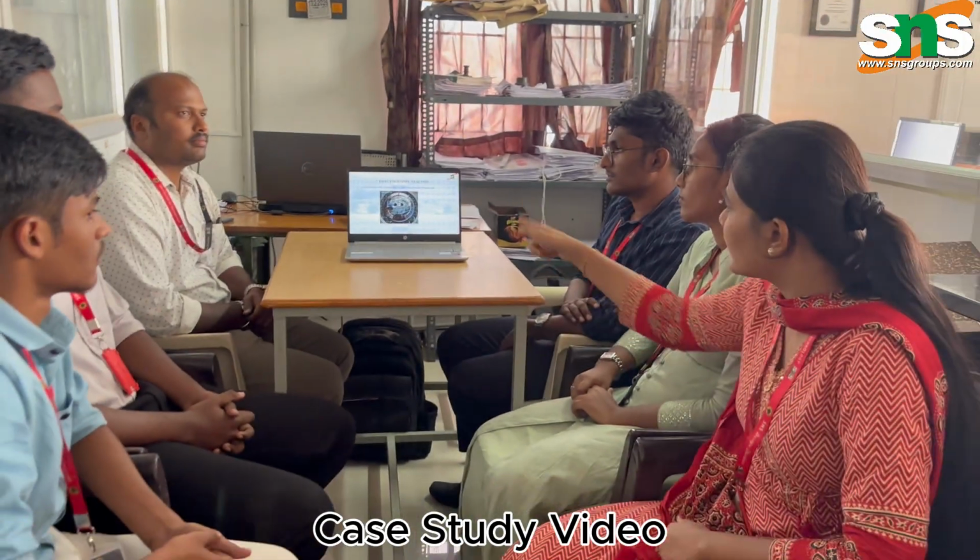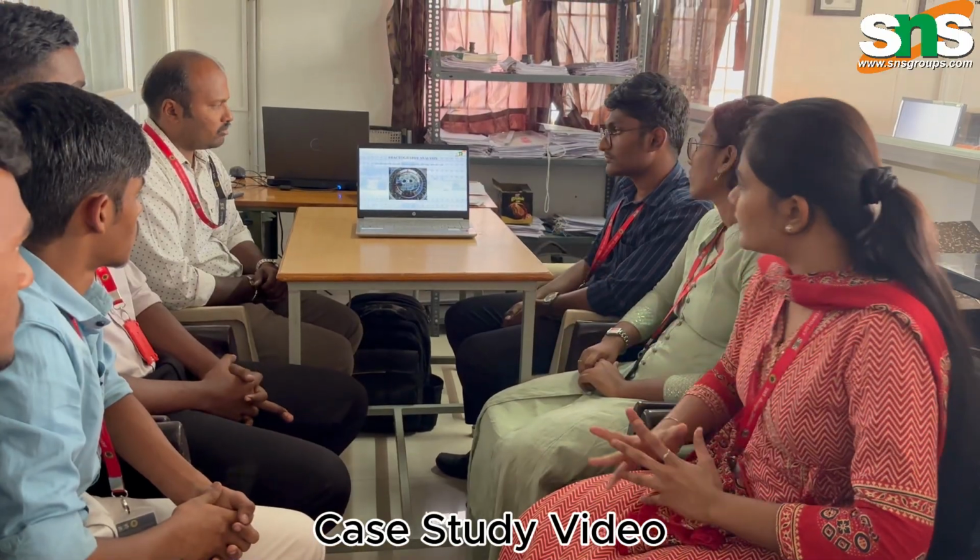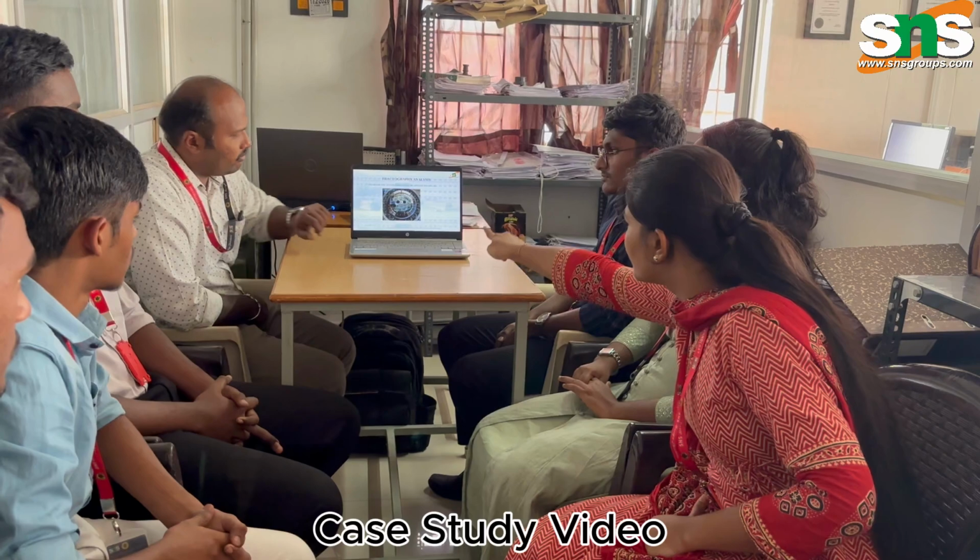This is the microscopic examination, where you can see the tempered martensite, etched with 3% nital. And this is the image of the broken shaft. The red arrow is where the crack begins and slightly moves inside, the blue arrow is where the crack started in the major part, and the blue box marks the broken area of the shaft.